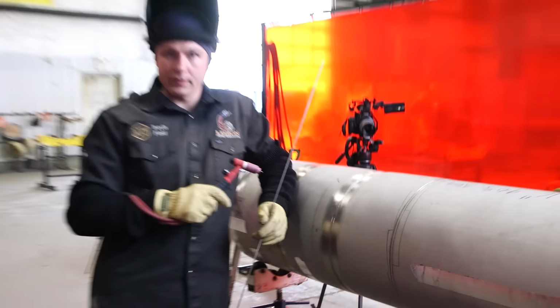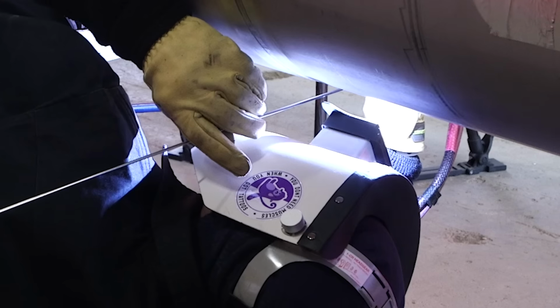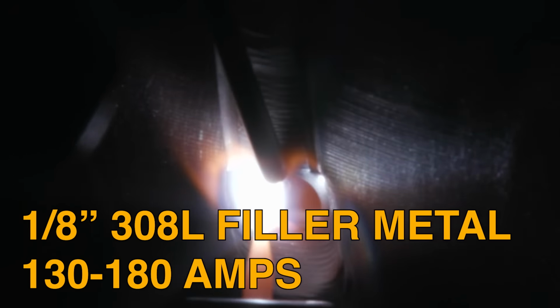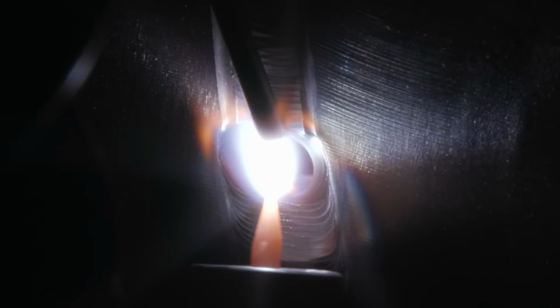Okay, so we're going to start doing the cap pass here from the bottom to the top, and then I'll pass off to JZ here to do his side. Could you turn the current down about 10? Or maybe up 5. So we're using 308L filler metal. Right now we're using 1/8. The root pass we did with 3/32 just to have nice control on everything over the weld puddle, even on large diameter piping, especially with the purge. If the purge is not very good, we'll still use 3/32.